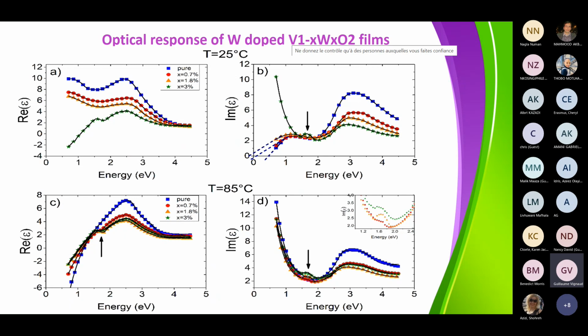Now the full lines here are the calculation of the dielectric component. Okay? And you can see that in the imaginary part, for the 3% at 25°, there is also a very nice Drude tail, which is not occurring here. And depending on the doping concentration, this is pure. So you see the gap here is at 0.5. If you go to 0.7, it's going to be close to 0. And if you go to 1.6% of doping, you can see that the gap is almost negative.